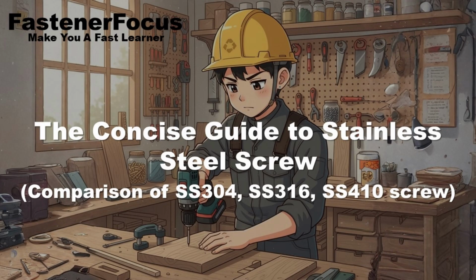Yes, if you put a 304 screw into an environment rated as C4, which is high corrosivity, or C5, very high corrosivity under ISO standards, which includes areas directly exposed to heavy salt spray or frequent use of de-icing salts on roadways, its service life will be severely compromised. It will typically fail within just a few years due to pitting corrosion. That's the line where 304 stops being acceptable.